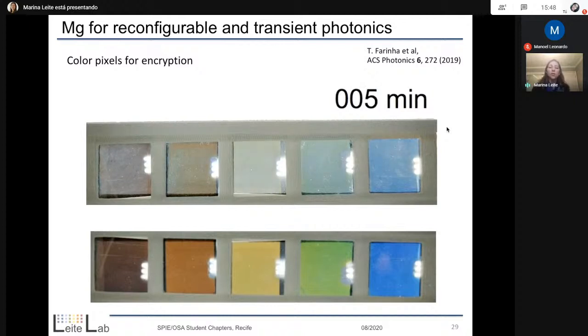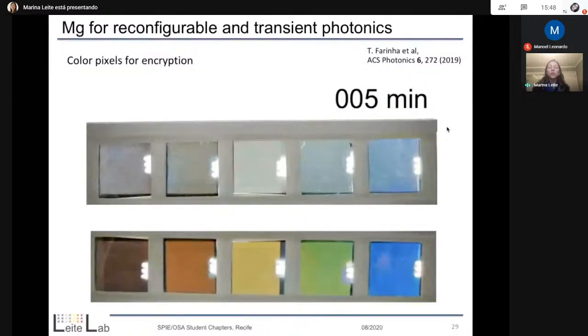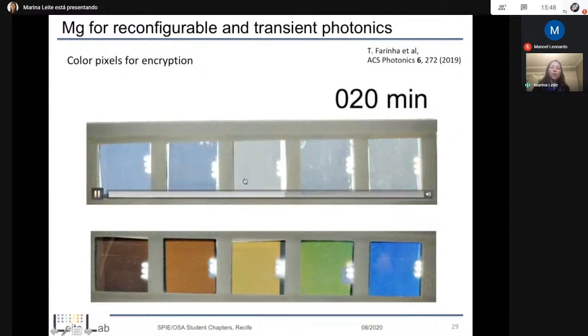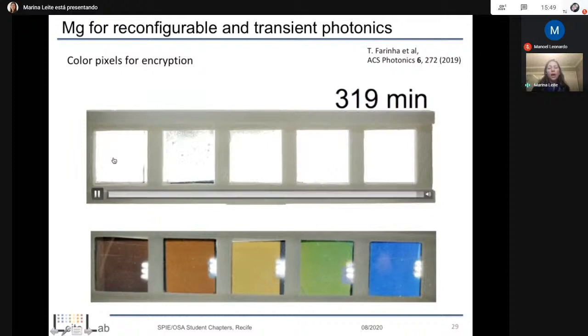It produces some hydrogen, a very small amount of hydrogen. It turns out that this hydroxide is earth abundant, and it's found in abundance in many, many countries. So that becomes really interesting. What you're seeing here now is that within 10 minutes, the colors vanished completely. As we speed up this video, I can just move on to the very last frame. What you can see is that now it's just white light. We're left with a glass substrate and that bright white light.